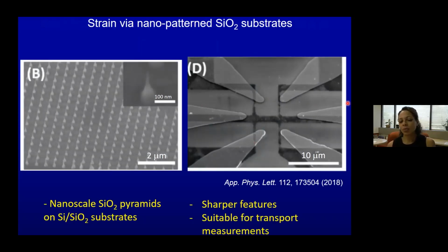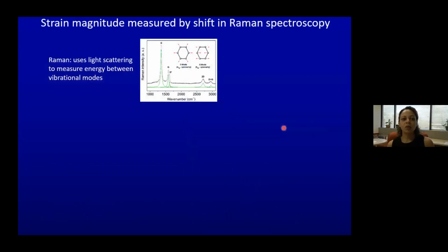Okay, so how do we know? I just said that we put the graphene on it. We knew that when the graphene was on PDMS that it was strained because we could see it adhering and de-adhering from the substrate. But what we really want is not to have adhesion or de-adhesion of graphene. We want the graphene just staying on the top and staying strained. So how do we know that the graphene is strained even when it's just pinned on top of these pyramids? Well, to do that, we use Raman spectroscopy.